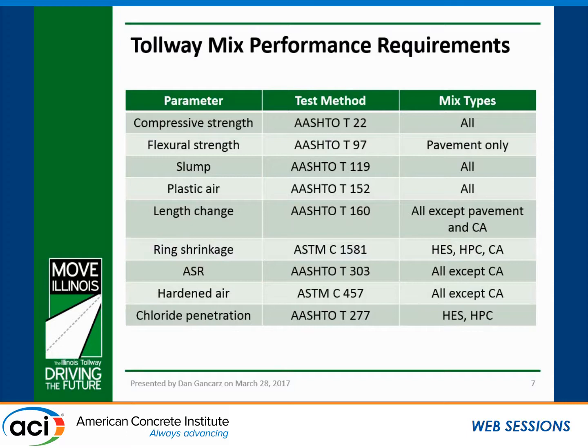We evaluate ASR on all mixes except the calcium aluminate mix. Similar for hardened air, all mixes except calcium aluminate, and then chloride penetration resistance on, again, our more high performance mixes, the high early strength patching and the HPC.